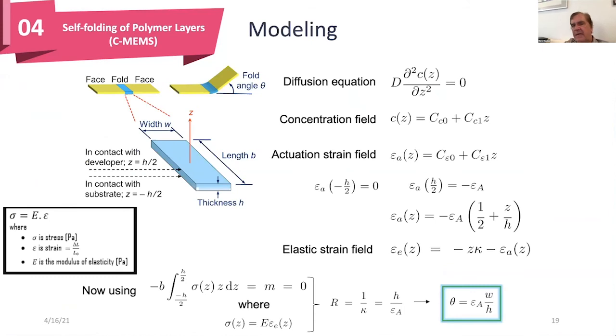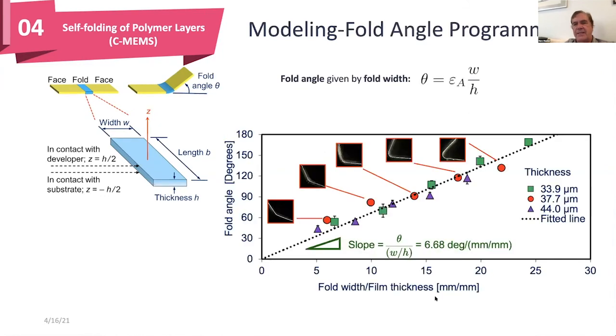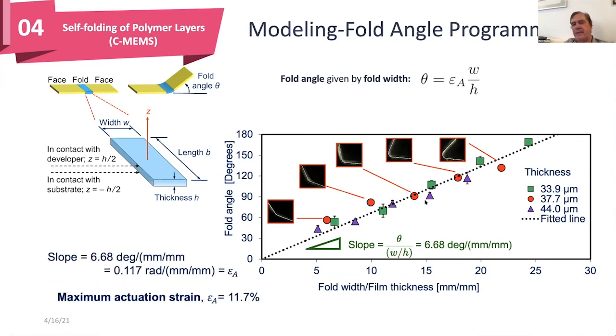And without going into the detail, we have the diffusion equation controlling the solvent evaporating, the concentration gradient of the solvent in the film, that causes really your actuation strain field. And it's that strain field that causes the bending angle theta. You can see here, this is fold width over fold thickness, millimeter over a millimeter, and that's the fold angle. And you can see these are experimental points. Our experimental result for the fold angle follows nicely the expected slope based on our little model. So that's the modeling fold angle programming exercise.